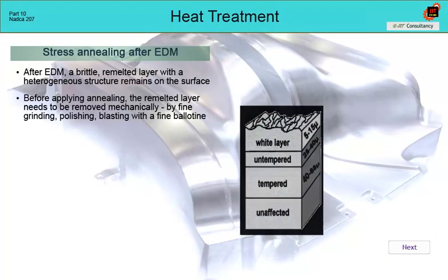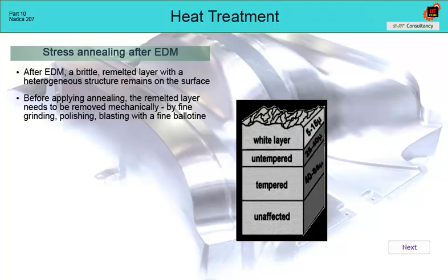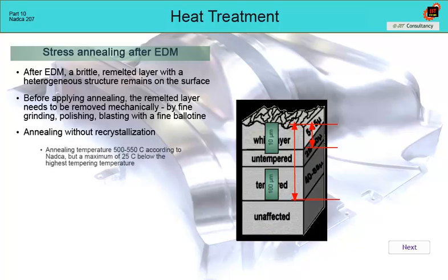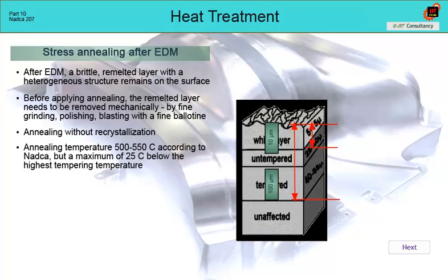The thickness of the white remelted layer is usually up to 10 microns. The total affected zone is then up to 100 microns. Annealing is without recrystallization, at a temperature of 500 to 550 Celsius. The highest permissible temperature is then 25 Celsius below the highest temperature of the previous tempering.